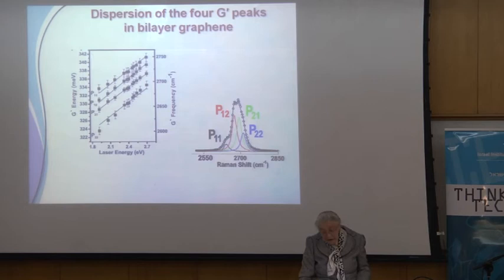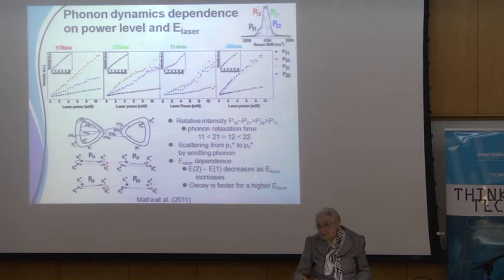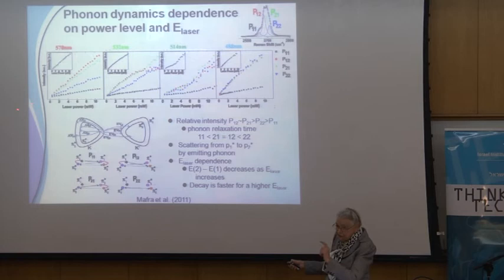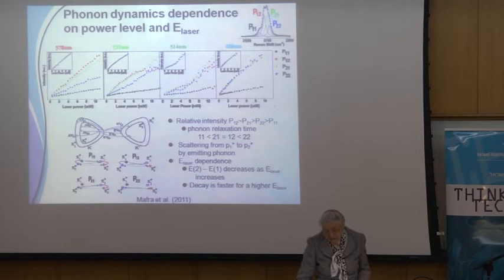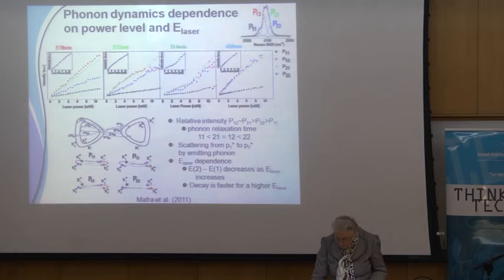So here is now putting power into the system, and then we can use that to make transitions between, you can see that, for the different laser energies. Here you have a low laser, the energy of the photon is low. So the states stay put. But then when we change and get the higher energy, then we can make transitions, induce transitions between them. You can see that we start mixing the states. So we could study this, even the dynamics could be studied by power levels in the static case because of the transitions that are made. This is maybe a little bit more complicated and technical than you want to hear, so I'll just get away from it.